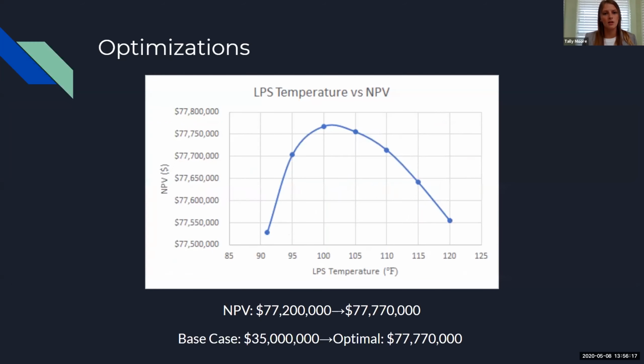And lastly, we went on to optimize our low pressure separator. We decided this couldn't be coupled with anything due to the fractionator already having the pressure being optimized. So we only optimized the temperature. And as you can see, the optimal temperature ended up being 100 degrees Fahrenheit. And this raised our NPV about 500,000. And as you can see at the bottom, from base case to optimal, we went from 35 million to about 78 million.